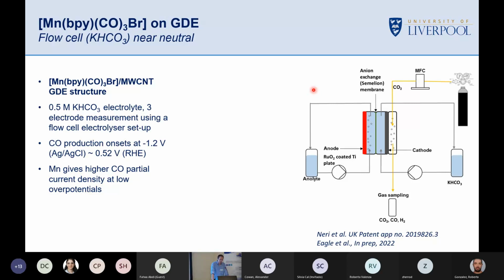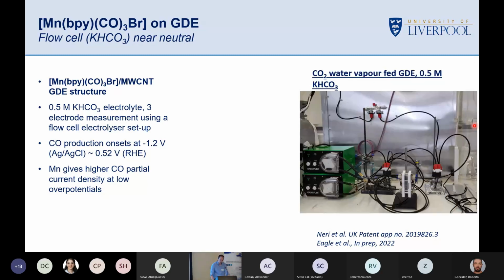We put our manganese complex on with its extra carbon filler. We mix it in with PTFE and Nafion to get the wetting right. There's a remarkable amount of work I never realized you had to do in controlling that. And we set this up with the flow cell, so it's a liquid electrolyte here. And this is what the cell looks like, and this is some very nice work.